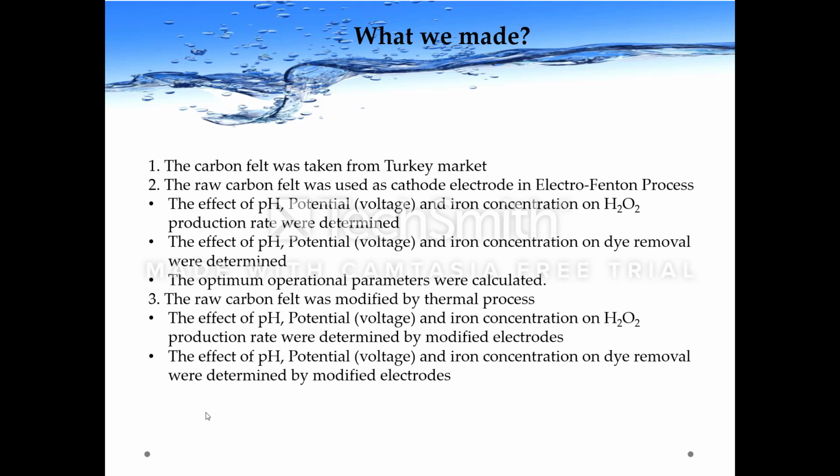In the second stage of our study, we modified the raw carbon felt by thermal processes, and we obtained four different cathodes by this method. Then we tried to find the optimum pH, potential, and iron concentration.